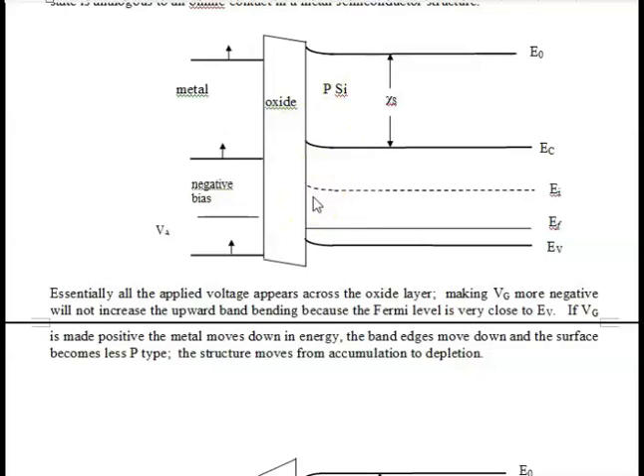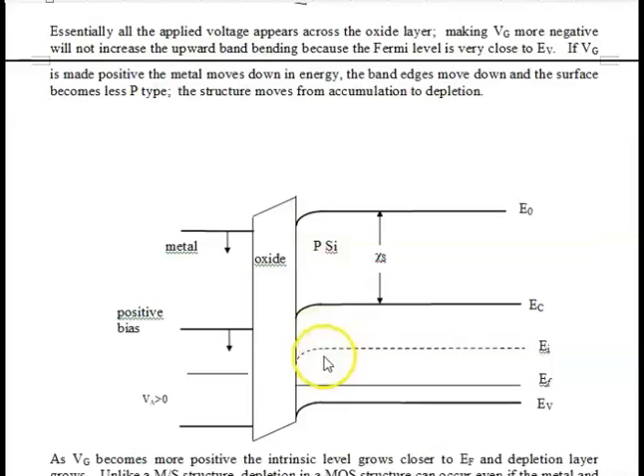region at all. Whereas here, the surface is less P, and the only way to make the surface less P is to uncover negative, and that's because it's P silicon, there are negative fixed ions at the surface. So here we have negative fixed ions right at the oxide silicon interface, and we have a situation of depletion.